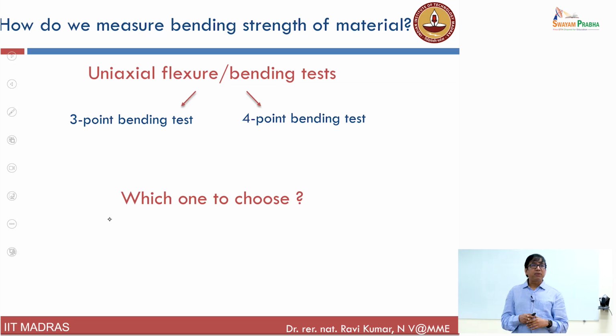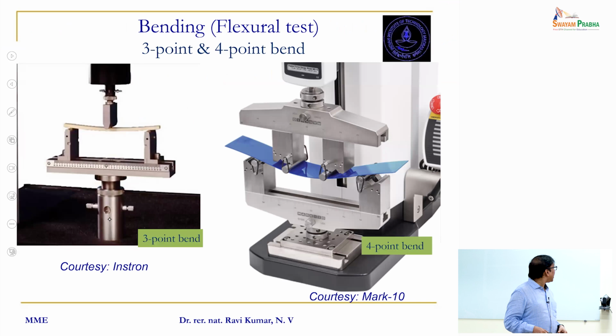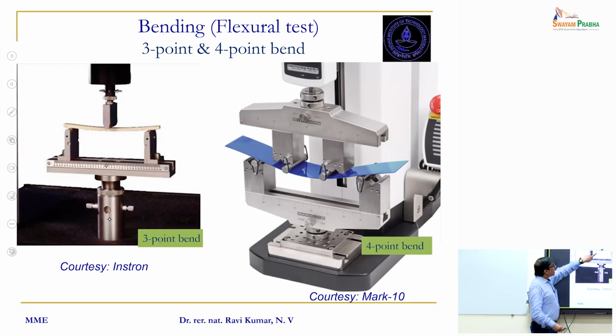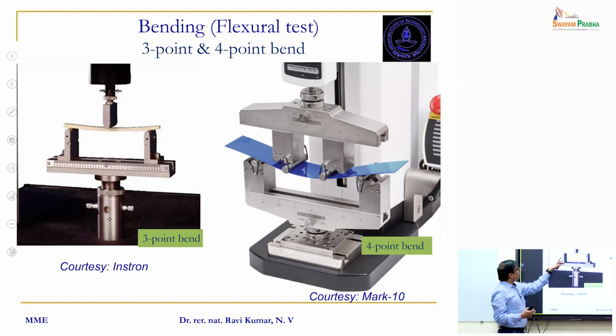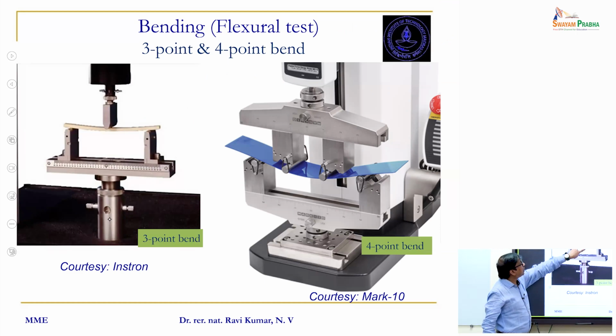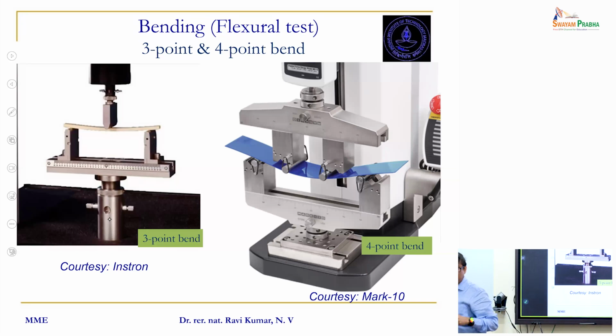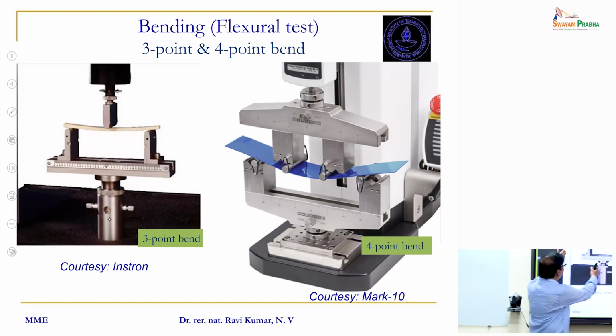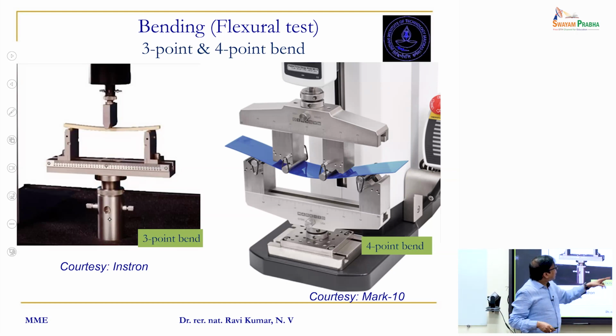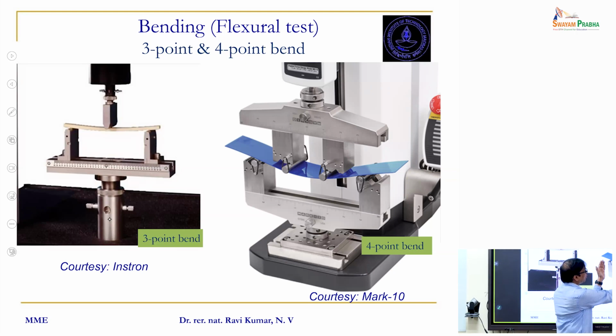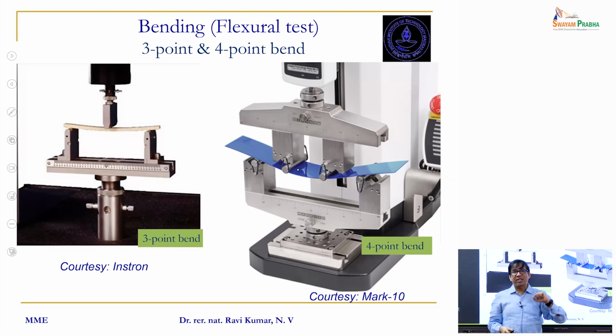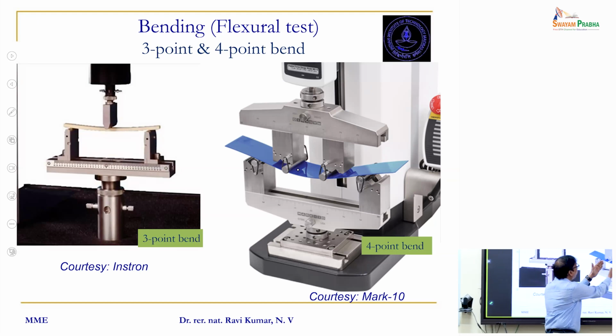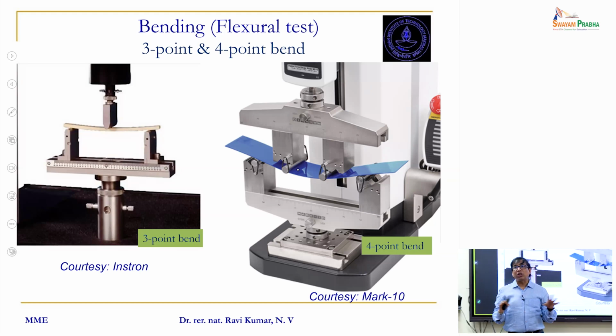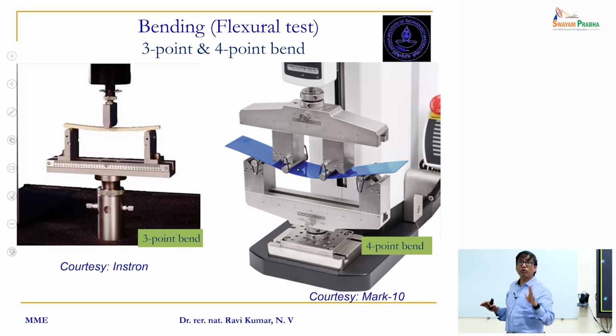But if you have come from an engineering discipline, you will know that, just to give you an idea, this is a 3-point bend test. So you have a sample, supported by 2 points at the bottom, and you have a central loading point. And what the distance should be and so on is determined as per ASTM standards. And this is a 4-point bend setup, again supported on 2 points, and you have 2 loading points in 4-point bending. What the span should be, what the loading point distance should be, all of them are specified as per ASTM standards. So you have to follow ASTM standards.